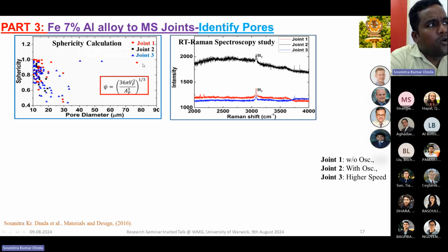Now, if you try to look at what the reason for gaseous pore formation is, or which type of gas is involved, we did a Raman spectroscopy study. I'm not an expert in Raman study, but what I know is that the laser source goes through the material throughout the thickness, and if there is any discontinuity, it will show a shift or peak. That is called the Raman shift. And from the literature, we found hydrogen is responsible for the gaseous pore formation.